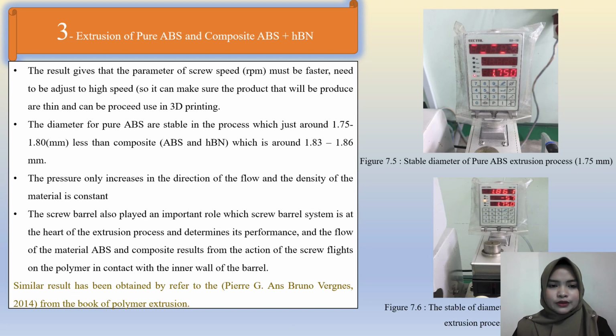Then for the third, extrusion of pure ABS and composite ABS HBN, the result shows that the screw speed RPM parameter needs to be adjusted to a higher speed, so it can make sure the product that will be produced is thin and can be processed in the 3D printing process. The diameter for pure ABS is stable in the process, at around 1.75 to 1.80 mm, less than composite ABS HBN, which is around 1.83 to 1.86 mm, as shown in figure 7.5 and also figure 7.6.